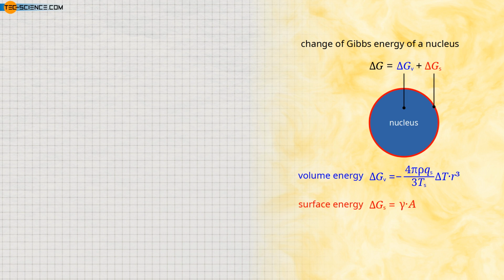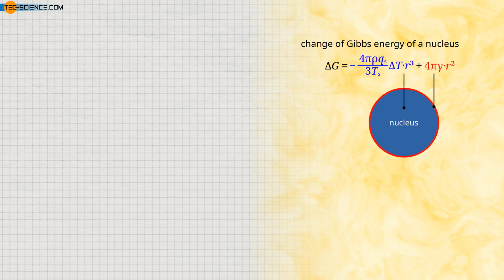The surface energy is the product of the surface tension gamma and the surface area of the spherical nucleus. Note that the surface tension is basically the surface energy per unit area. Multiplying the surface tension by the surface area of the nucleus therefore gives the total energy of the nucleus surface. The surface area of the spherical nucleus is determined by 4 pi r squared. Overall, the change in Gibbs energy of a spherical nucleus with radius r at a given supercooling delta T can be determined as shown. The interpretation of this equation is discussed in more detail in the following.